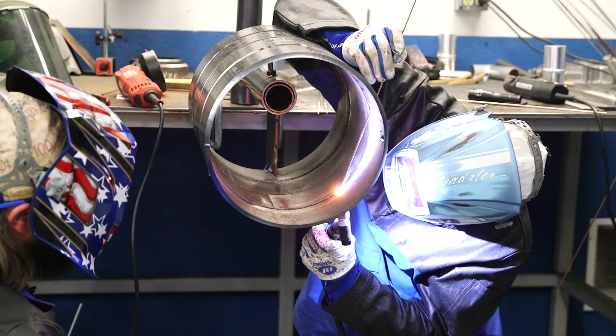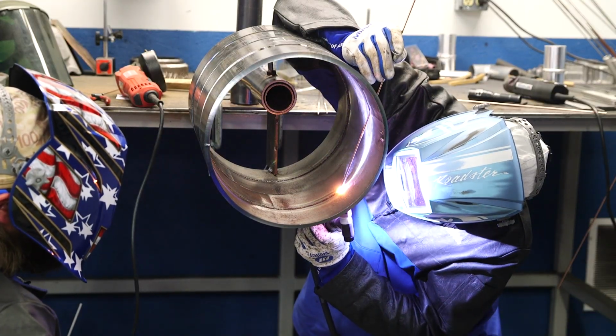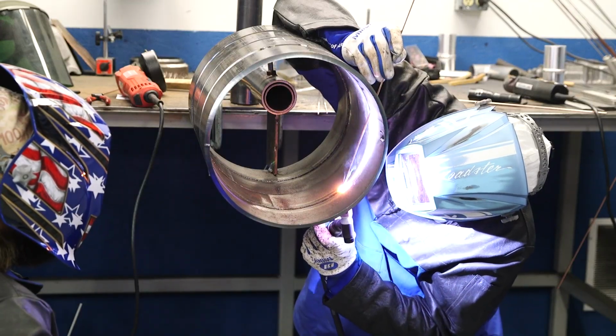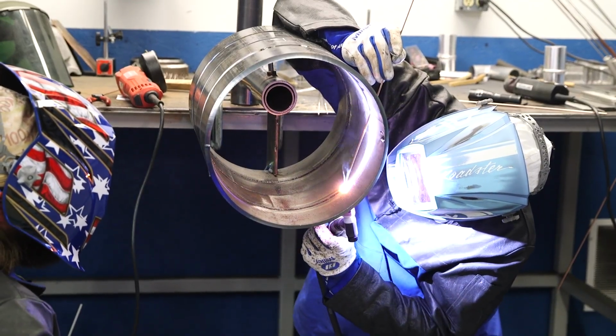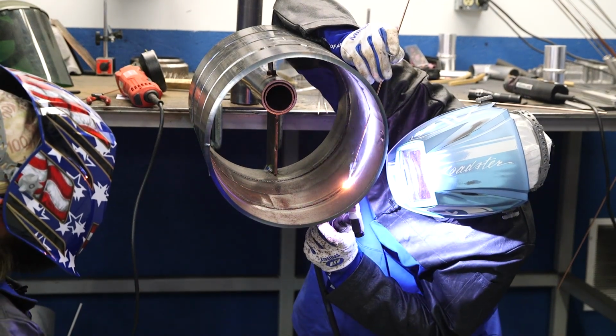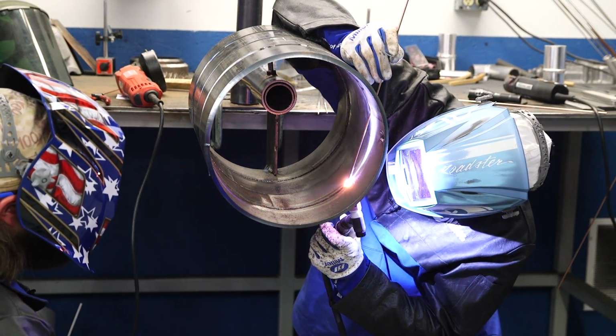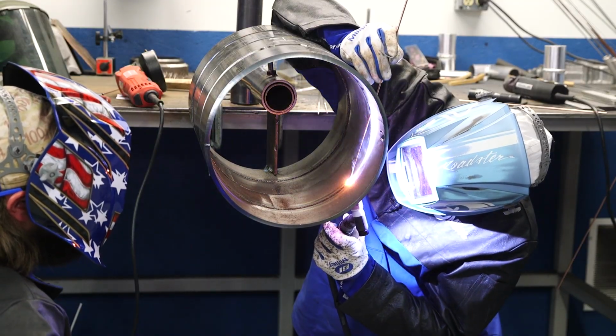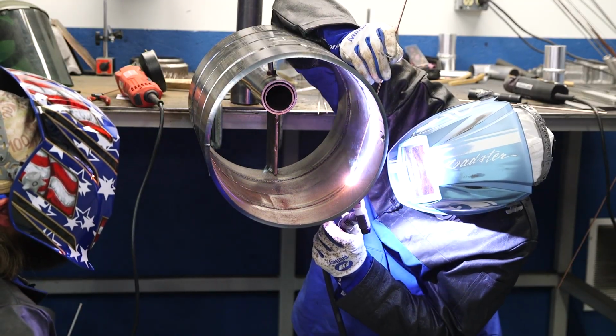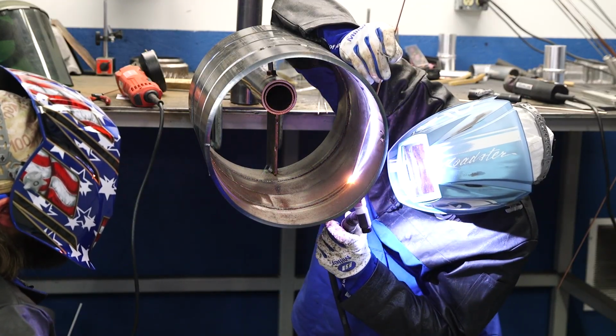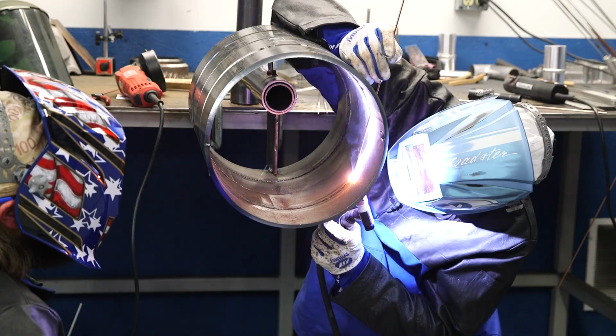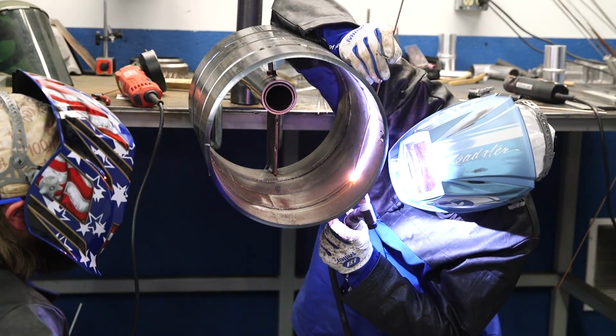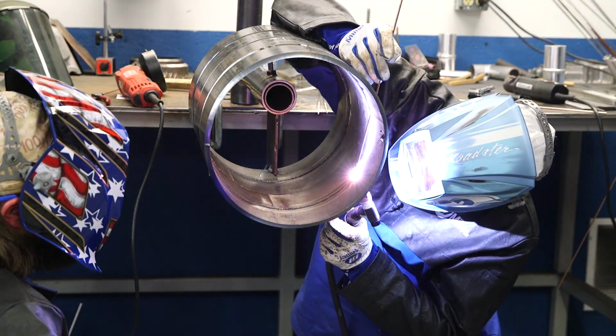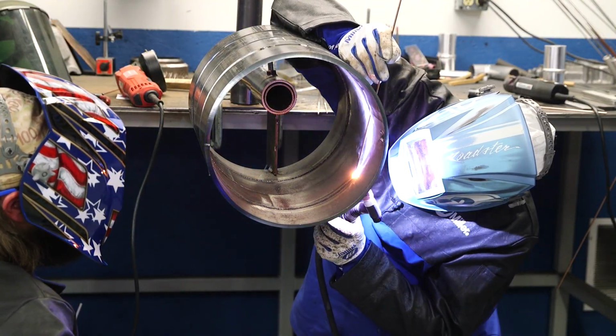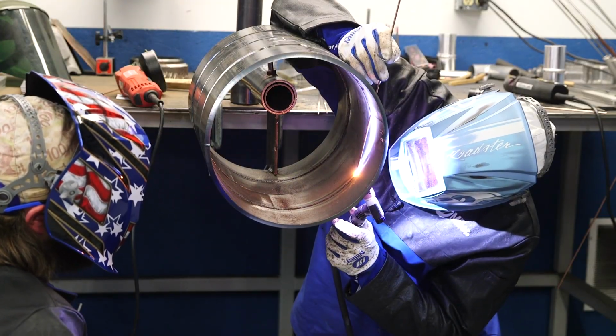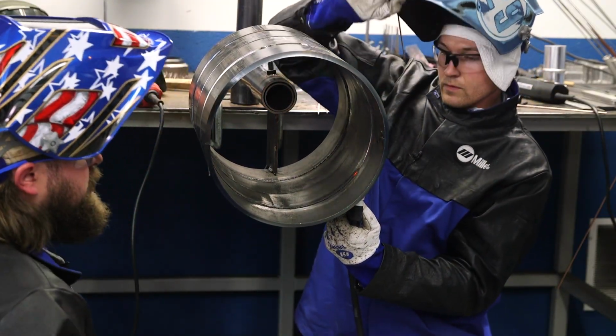So depending upon the alloy you're welding, the filler wire you're using, purging, no purge, it really dictates your technique, and you would kind of have to adjust on the fly as you get used to the material. As well as the stainless 304H, we did some 2.25% chrome. And with that material, you can purge it, but you don't have to. So we did our position welds without a purge, being the low percent chrome. But chrome being a little more sluggish, as well as having those oxides, the constant feed was a crucial technique with that material. Otherwise, we found that without introducing the deoxidizers of the filler wire, the puddle became really dirty and sluggish and didn't want to fuse properly.